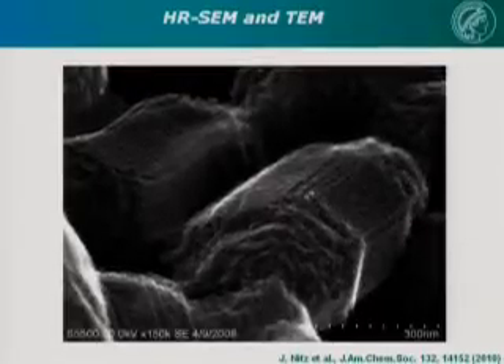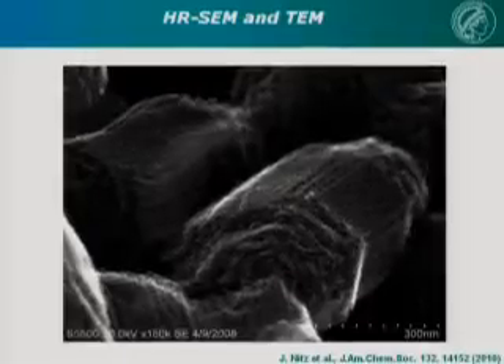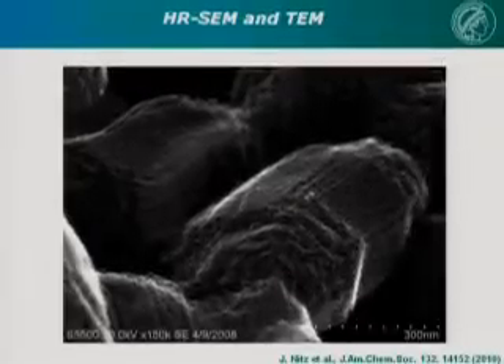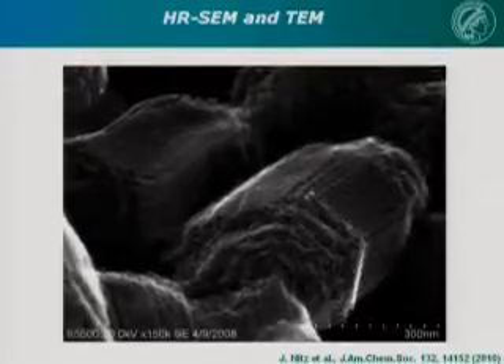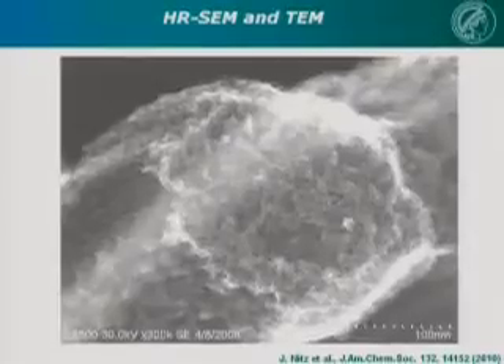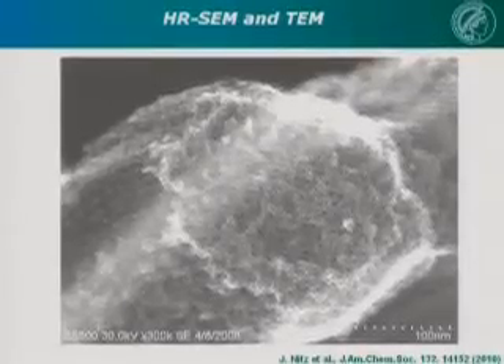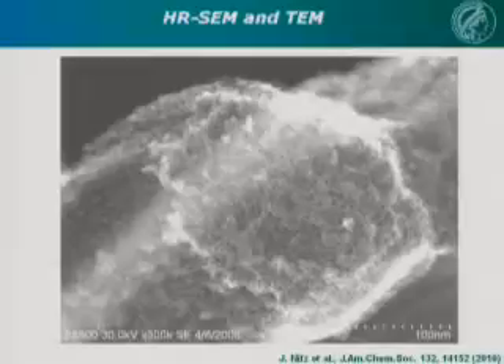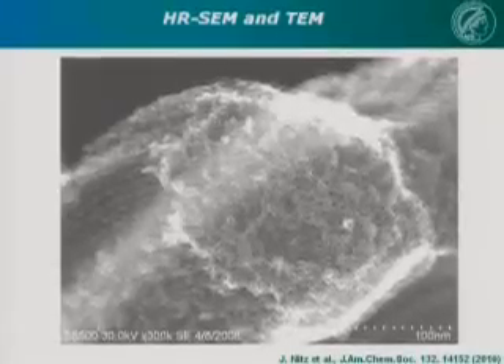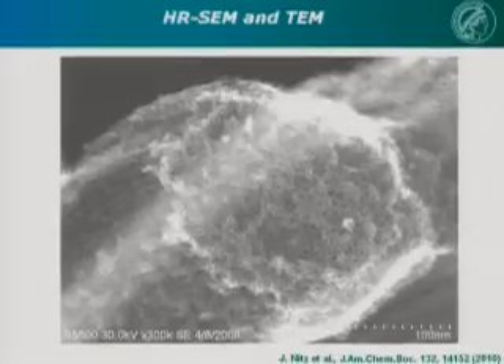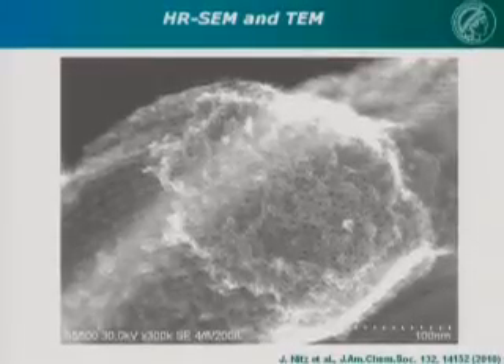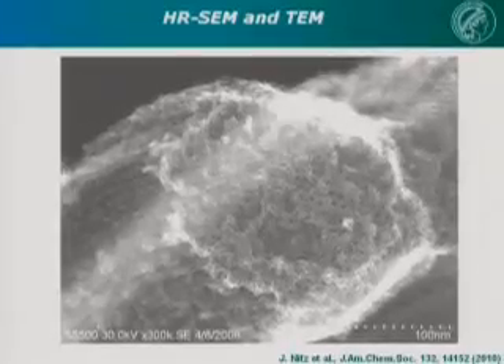We are looking here at these hexagonally ordered carbon tubes. The tubes run in this direction. These are the carbon tubes, and you can actually see the carbon tubes in high-resolution scanning electron microscopy. I'm always amazed what scanning electron microscopy can do nowadays. So you get nanometer resolution in a scanning electron microscope. This is actually not a badly done image with lots of charging.